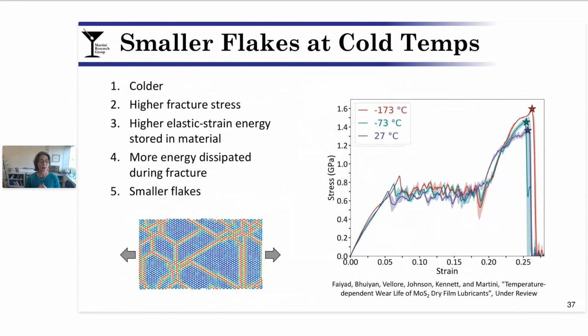The first thing we did was try to understand why the debris might be smaller when it's cold. To do this, we performed simulations of simple tension on MoS2 sheets, as shown in the lower left. Just a quick note that looking at the stress distribution in the sheet, we already do see these triangular patterns. But perhaps more importantly, in the stress-strain plot on the right, you can see that as we go from room temperature to colder, the fracture stress increases. Higher fracture stress is associated with more elastic energy stored in the material, and therefore more energy dissipated upon fracture, and theoretically smaller flakes or debris.